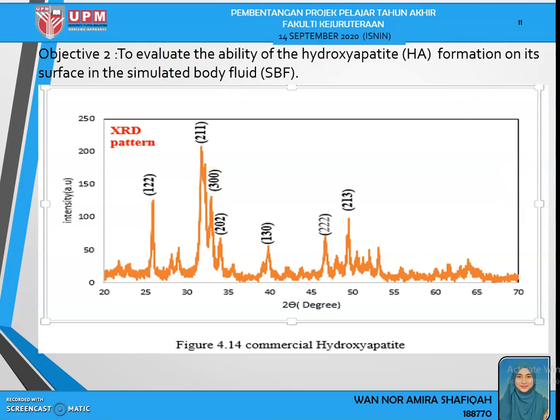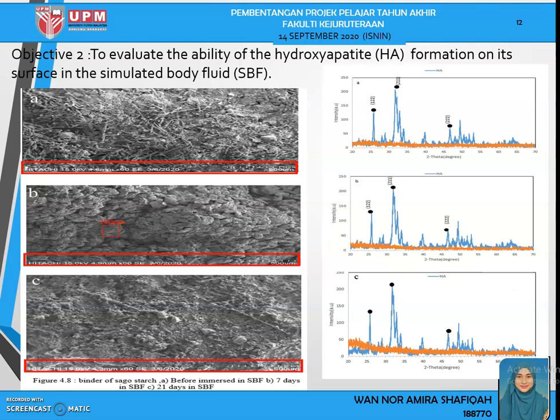This shows the hydroxyapatite formation, so that we can compare the XRD of HA with the one that we did with our tablet. So this is the SEM image for the sago starch as a binder. Based on this figure, it shows that the BG is formed by a long tubular structure